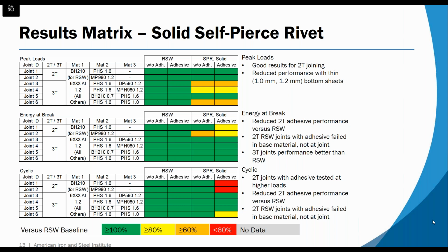Moving down to the energy results, we saw that in the 2 thickness, there was some reduction in effectiveness in the adhesive joints, but not dramatically so in most cases. Interestingly, in the 3 thickness joints, even though we saw some peak load reduction, the energy absorption was actually equal to or better than the resistance spot weld baseline in every 3 thickness case. So that was an unexpected but interesting result.